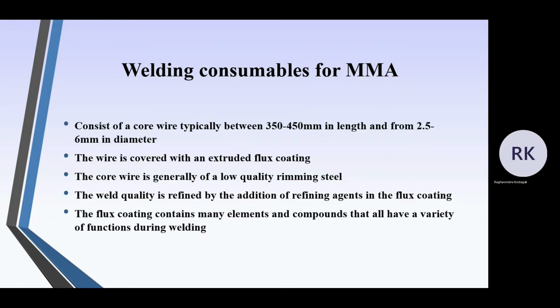So welding consumable for SMAW consists of core wire, typically between 350 to 450 millimeters in length and from 2.5 to 6 mm in diameter. You can also see more details of this in CSWIP class chapter 16, if I'm not wrong. Then the wire is covered with extruded flux coating. Then the core wire is generally of low quality rimmed steel. The weld quality is refined by the addition of refining agents in the flux coating so that it gets embedded into the welding. And the flux coating contains many elements and compounds that have a variety of functions during the welding.